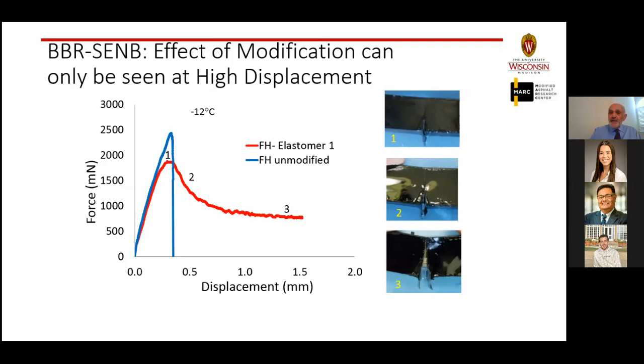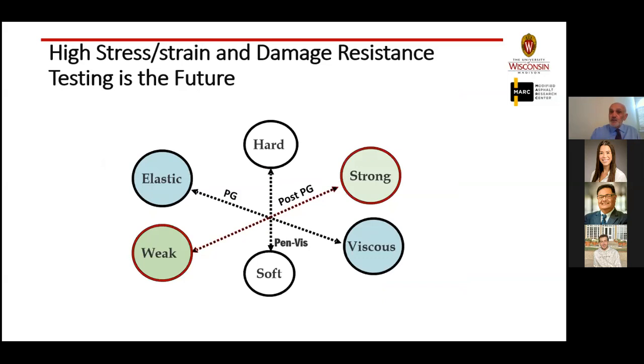If you have stretched this material to here, and then the next day the sun will come out and it warms up, we all know binders can actually heal. And therefore, by limiting the crack propagation or limiting the crack width with these polymers, we can see significantly longer life of these pavements. So what did we have to do here? Not much really. All we did is the same creep test or a similar test with a constant rate of deformation. And you can see the huge differentiation between the two materials just because we went into the damage, the large strain domain, if you will.